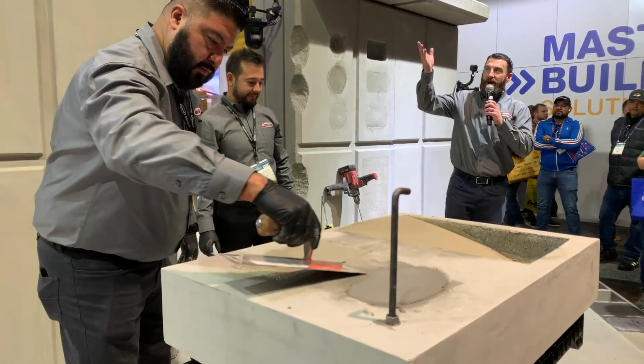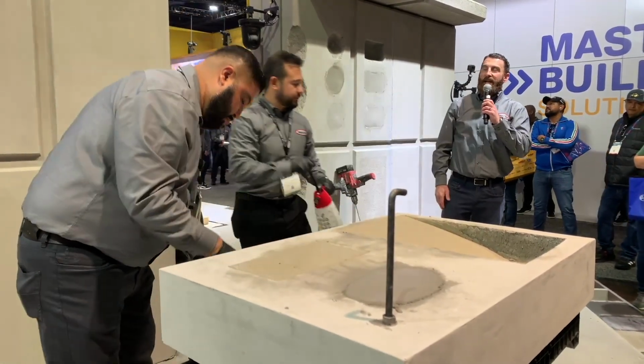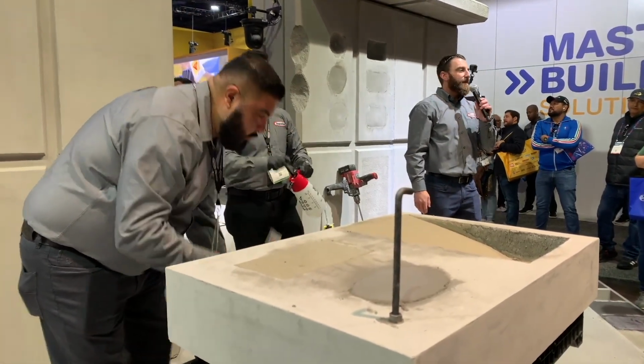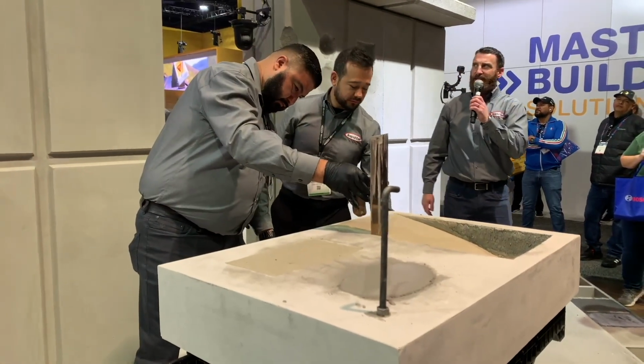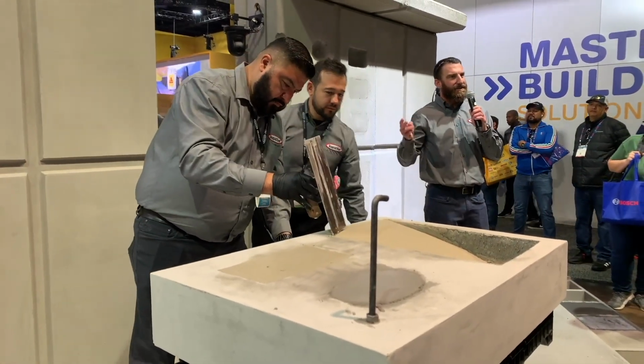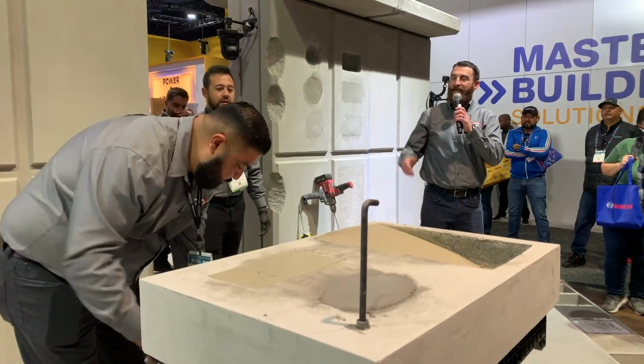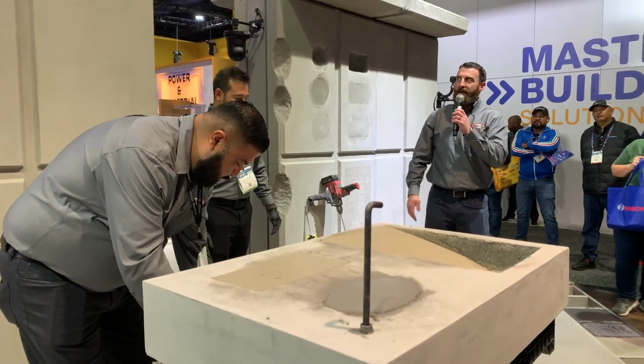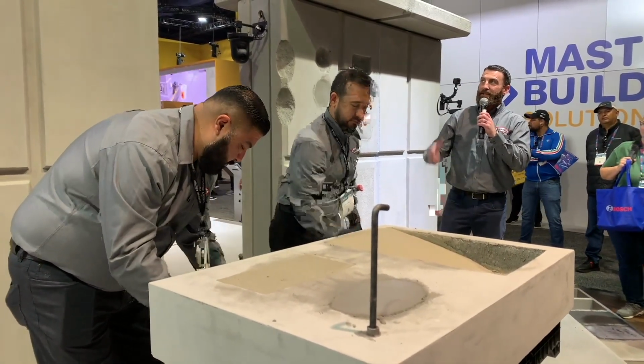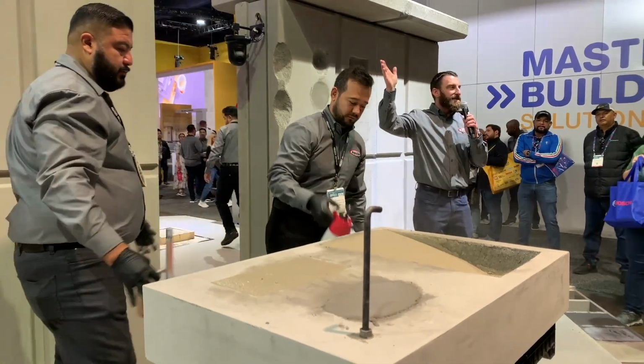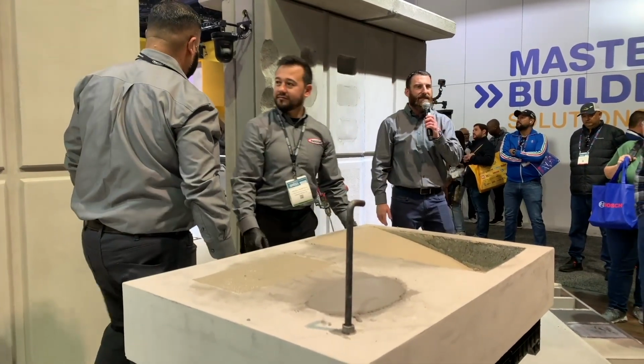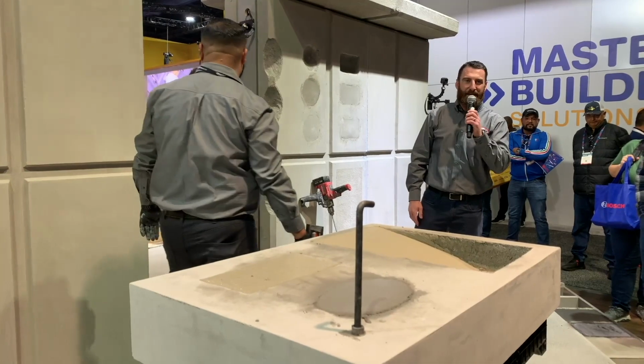So we've got a few projects up on the screen. The Highway J Bridge in Missouri. This one got top marks by the National Bridge Inventory for deck, substructure, and superstructure because they used the Rapid Set Cement All to grout the keyways. The requirement on this project was 3,000 PSI in 24 hours, and the Rapid Set Cement All achieved over 7,000 PSI.